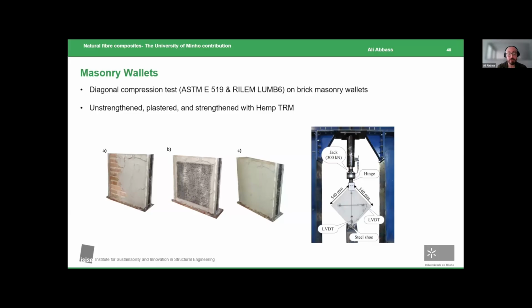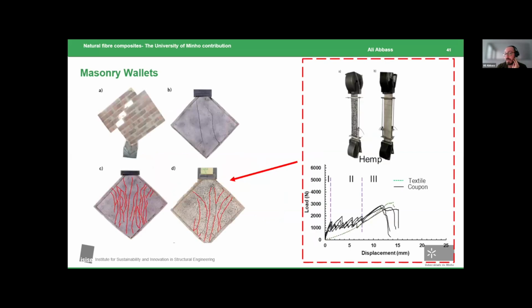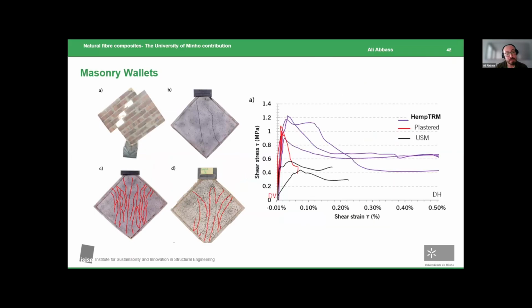the nanocomposite coated textile, and we tested a reference wallet, non-reinforced with anything, then a wallet reinforced with our system, and one with only the matrix, just to understand the effect of the reinforcement and its efficiency to accommodate the diagonal kind of cracks. So here you would see the results. We have vividly the ductility, the pseudo-ductility obtained with the inclusion of the fibers, and this is very important when we're talking about seismic. Of course, this is not seismic because this was done monotonically, but it gives an idea that this system can function up to an extent in a seismic region.